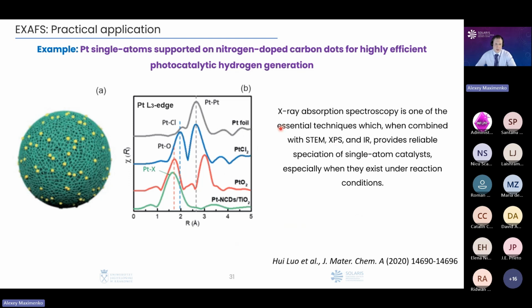Where EXAFS could also be used quite efficiently, and it is now a quite popular topic, is single atom catalysis. If we speak about single atom catalysis, it means one atom connected to some kind of surface, and it does not have any neighbors. For example, platinum single atom catalysis in comparison to platinum nanoparticles. When it is nanoparticles, you definitely should have interactions such as platinum-oxide interaction and platinum-platinum interaction. Or if it is a pure metal, you will have only platinum-platinum interaction. And when we speak about single atom catalysis, we could see only one interaction, between the platinum atom and the oxygen on the substrate.